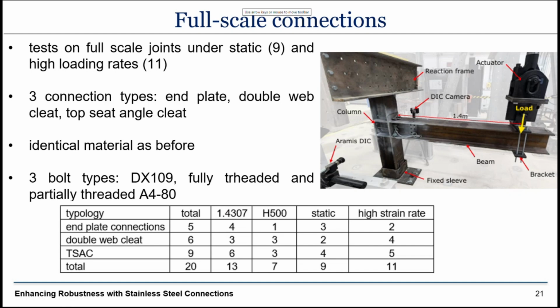So having looked in detail into the components of lap joints and T-stubs, which are key components in all connections, we proceeded to doing full-scale connection tests. So we did a total of 20 tests in Birmingham, 9 under static conditions and 11 under high loading rate conditions. This is the overall setup we used. So we had a column that was basically connected to a sleeve that we had anchored to the strong floor of the lab, and a beam that was loaded at the end at about 1.4 meters with an actuator.